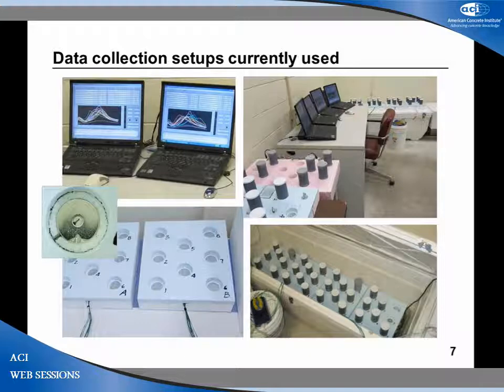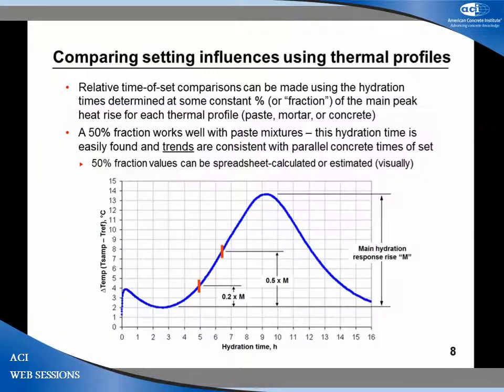You can actually use a simulated field temperature environment in a laboratory thermal cabinet or a water bath type curing tank. And here's what the data collection looks like when we're doing a lot of this at once. The thermal profile, which everyone is probably familiar with, looks something like that from changing temperatures of these materials over time. And in order to evaluate the setting trends of different changes one mix to the next, we compare the relative timing of what's happening in the main peak of hydration, which is contributed primarily by tricalcium silicate hydration. And you'll hear the term fraction. There'll be a certain fraction of the main peak that might be used for evaluation. A convenient one to use is 50% of this thermal rise.